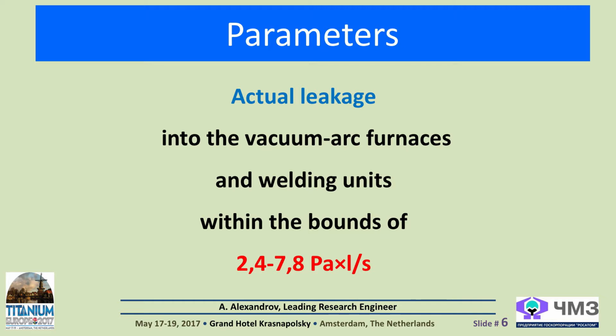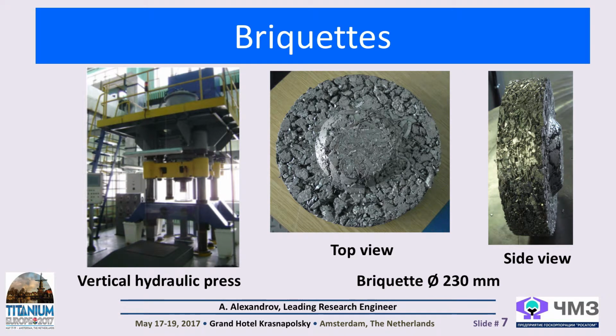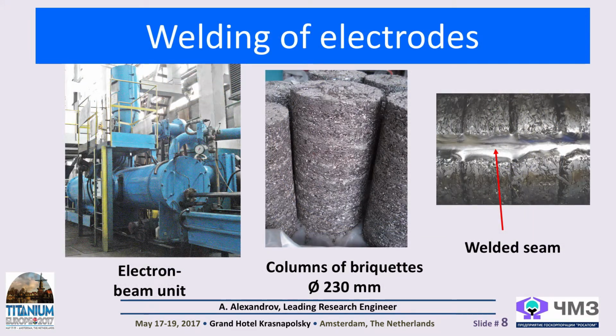On the basis of the charge calculation, briquettes of diameter 230 millimeters were pressed on a vertical hydraulic press. To obtain strong briquettes from a large number of charge components, they were placed in a press matrix in a special way. The density of briquettes was 3.5-3.6 grams per cubic centimeter, or about 66-68% of the theoretical value. The obtained briquettes were stacked in columns, and longitudinal welded seams were applied to the lateral surface of the column in the electron beam unit, thus forming the consumable electrodes of the first remelting of sufficient mechanical strength.